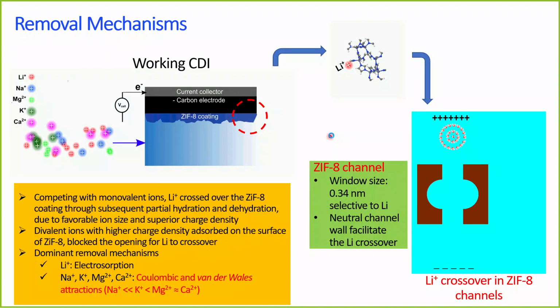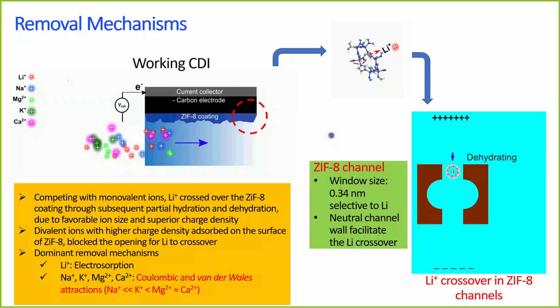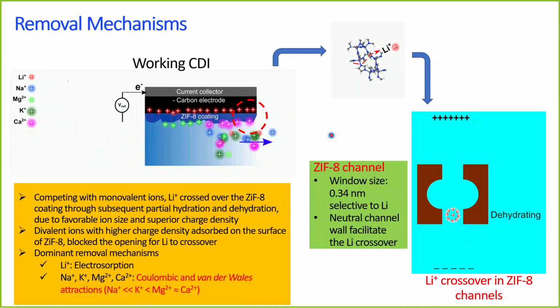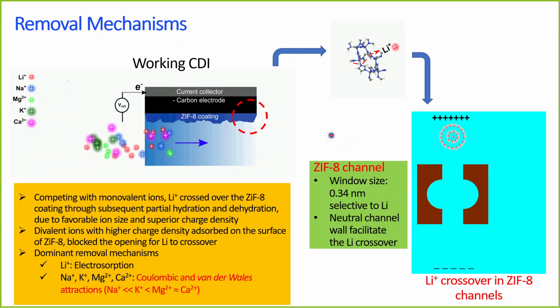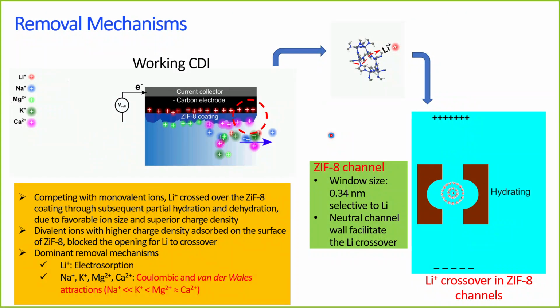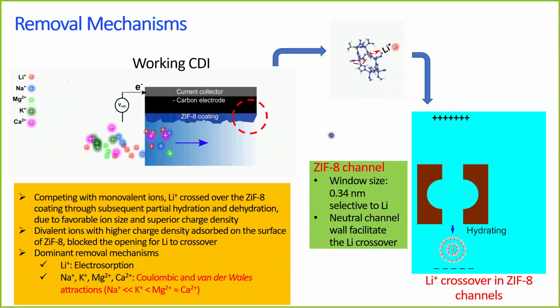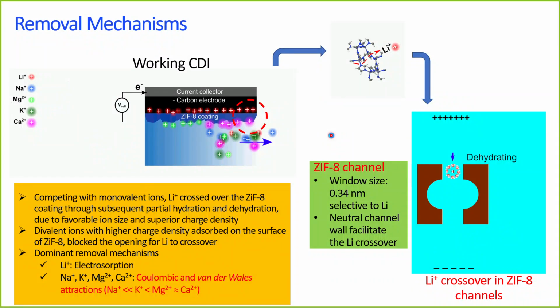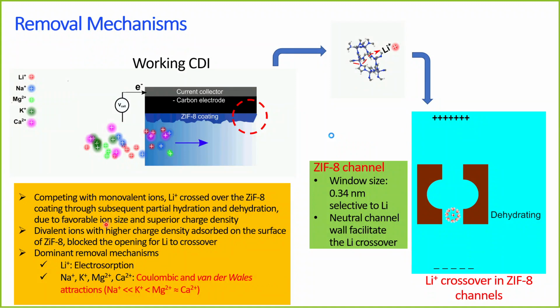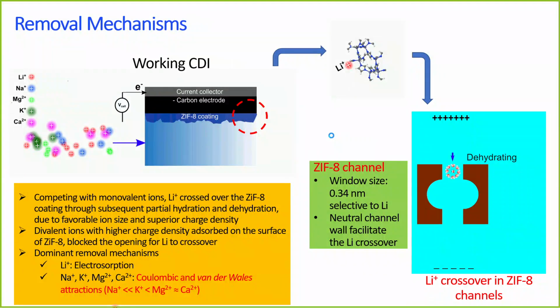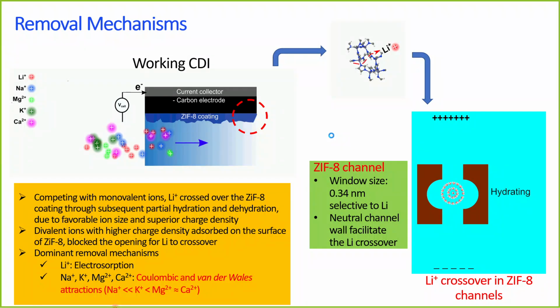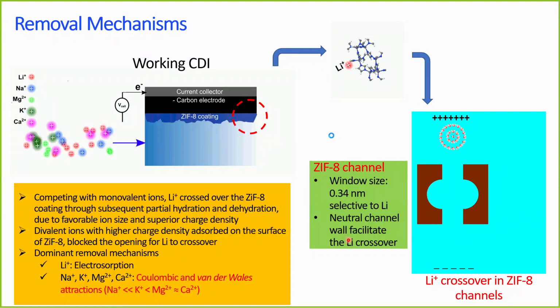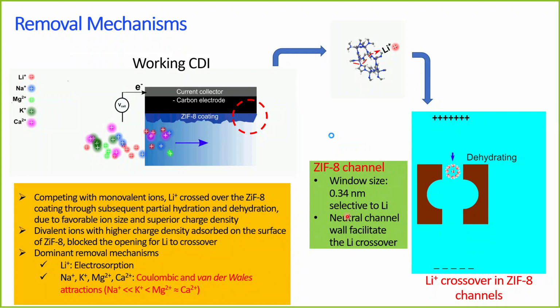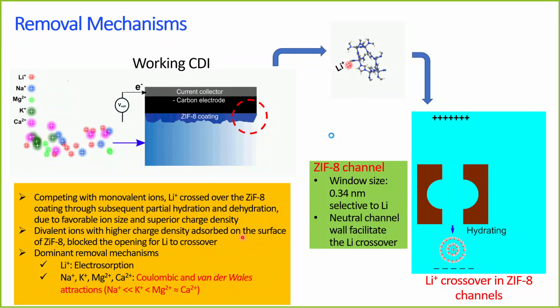So this is the removal mechanism. What happened is the competition with the monovalent ions. So lithium crossed over the ZIF-8 coating with the subsequent partial hydration and dehydration due to favorable ion size and superior charge density. And the dominant removal mechanism, so for lithium it is more of an electrosorption we can achieve, and for sodium, calcium, magnesium, and potassium, coulombic and van der Waals attraction were the more dominant removal mechanism for this material of the MCDI with ZIF-8. So ZIF-8 is a very useful material to increase the overall selectivity of lithium in seawater brine.